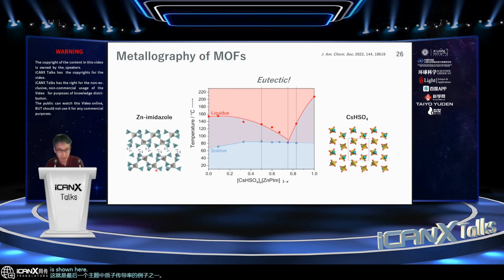So we have zinc imidazolate, the MOF, which has a melting temperature close to 160. On the other hand, as introduced at the very beginning, there are also metal salts showing very high proton conductivity, which we call solid acids. So these two of them can be mixed. And then we can develop the phase diagram like this. This right-hand side is pure cesium hydrogen sulfate. This left-hand side is pure zinc imidazolate, the MOF. But by controlling the ratio of the mixture, you can see the melting temperature changes. And we also see some solidus line. So this behavior is a very typical eutectic behavior.